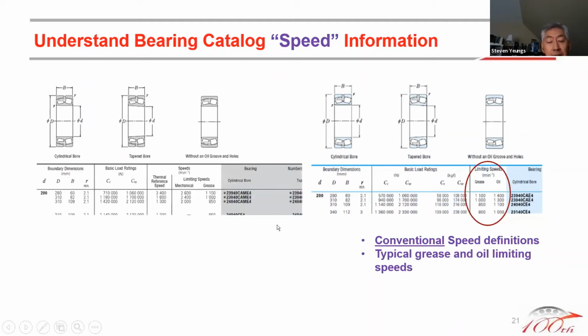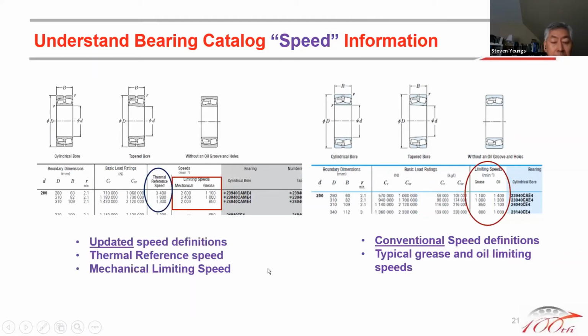But when you look at a newer catalog, you'll see updated speed definitions have been put in, under thermal reference speed and under mechanical limiting speed. And there's also the grease information as well. You can see the grease information remains the same, but there is new information indicated that, for example, under thermal reference speed, it's 1,400 and 2,400, and under mechanical speed, it's 2,600. So when you look at these definitions, 2,600 versus 1,400, you can actually operate at a speed of almost 100% increase. And why is that?